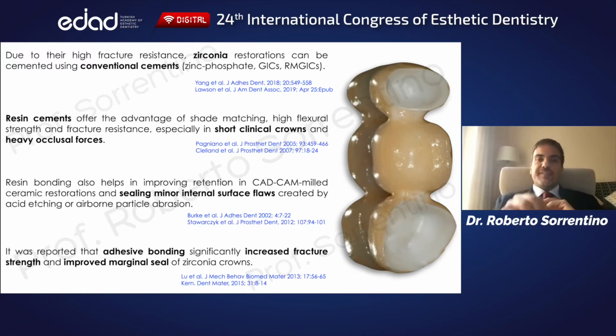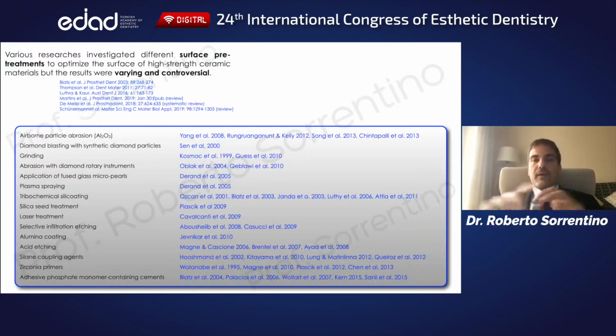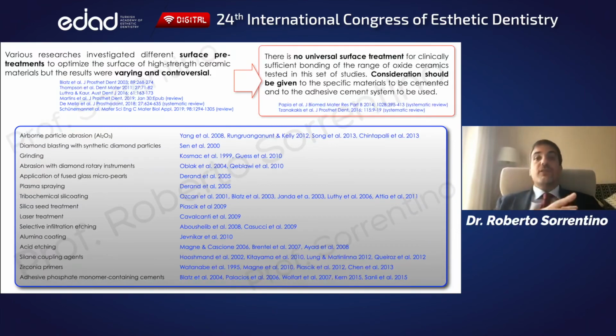A strong resin ceramic bond relies on both micromechanical interlocking and chemical bonding, and insufficient surface modification could negatively affect the retention of ceramics. Several surface treatments for zirconia were described in the literature, as you can see in the slide, from abrasion to tribochemical techniques, from grinding to plasma spraying, and from zirconia primers to laser treatment. But data are not conclusive yet.